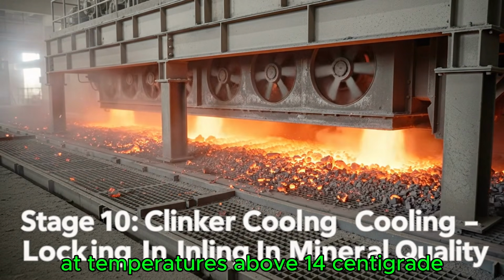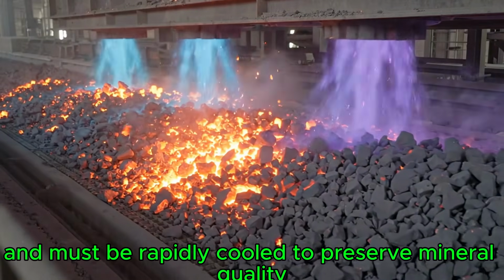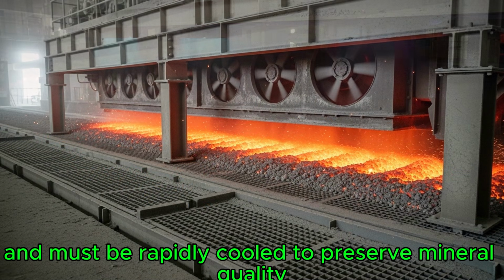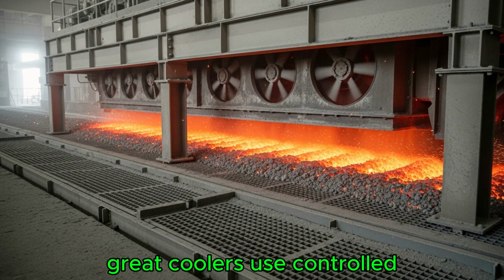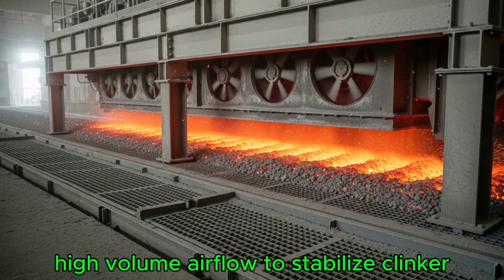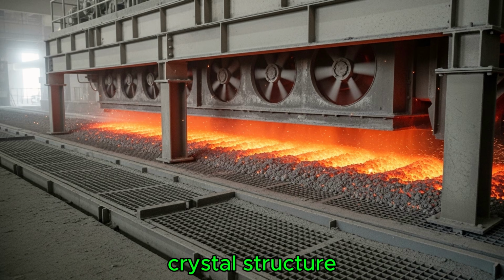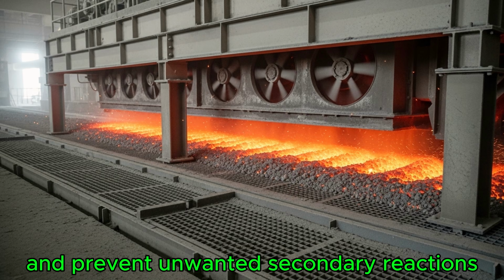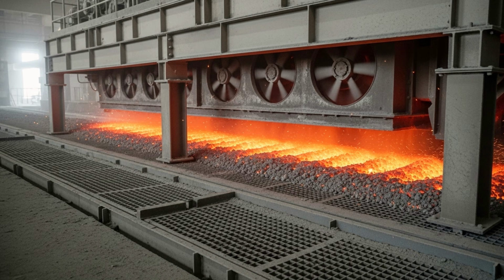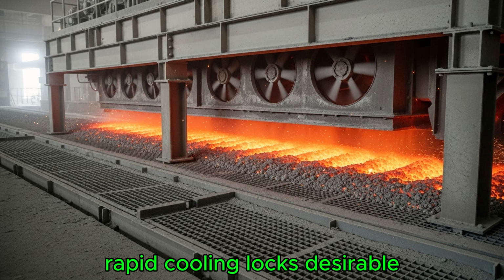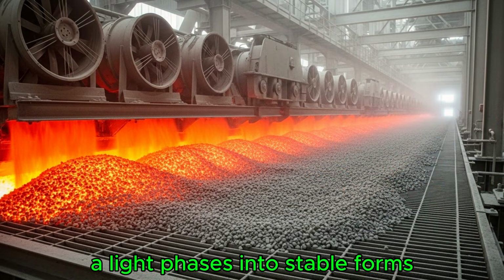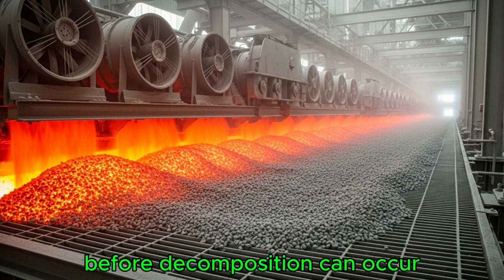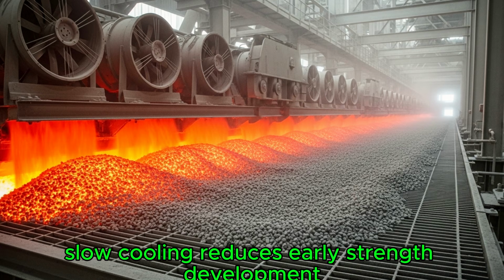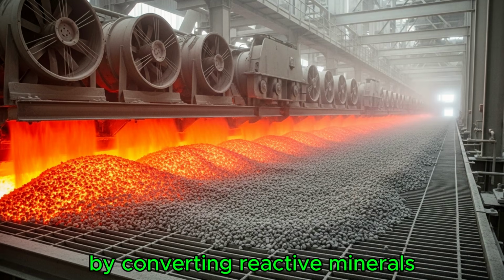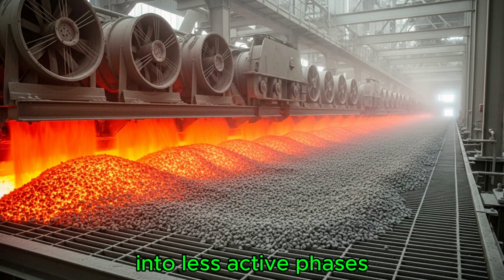Fresh clinker exits the rotary kiln at temperatures above 1400 degrees Celsius and must be rapidly cooled to preserve mineral quality. Grate coolers use controlled high-volume airflow to stabilize clinker crystal structure and prevent unwanted secondary reactions. Rapid cooling locks desirable alite phases into stable forms before decomposition can occur. Slow cooling reduces early strength development by converting reactive minerals into less active phases.